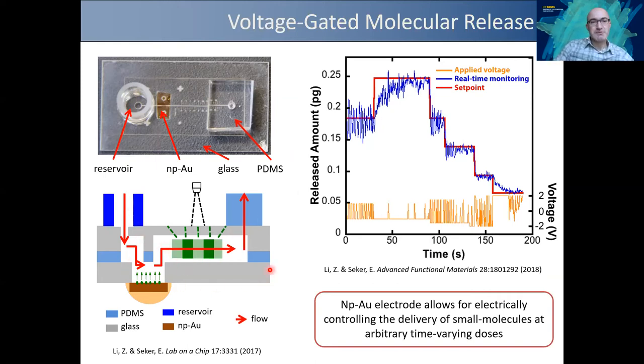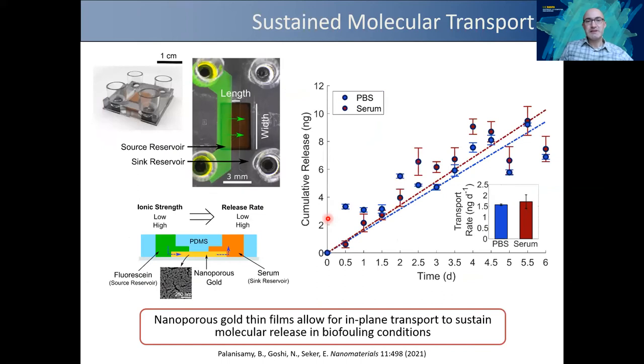We've built a basic microfluidic chip to test this. So you have a microfluidic chip where the nanoporous gold is attached to the bottom. There's flow, and we can measure the fluorescence with an epifluorescent microscope. We create a controlled scheme where you can read the fluorescence intensity and control the voltage that you would apply to the electrode to control the release. So you can, for example, prescribe a set point release dose, and you can apply a control voltage to control that release. And it tracks really well with the set point. So this now enables us to do electrical control in very small doses and arbitrary time varying doses. So think about, for example, in the case of epilepsy, you may be able to turn on the release or stop it if necessary.